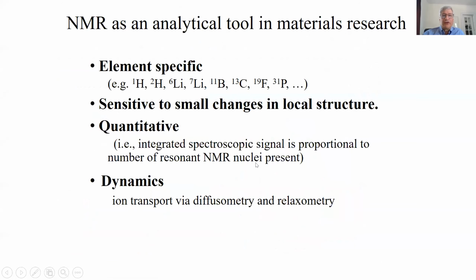So our laboratory uses nuclear magnetic resonance as a primary analytical tool. It turns out that nuclei that you can look at are very common in battery materials. So this is kind of a happy coincidence. The NMR technique is very sensitive to small changes in local structure. It's quantitative. We can look at various peaks of the NMR spectrum and get an idea of the so-called phase diagram, the different phases that make up the material that we're looking at. It's also very good for looking at dynamics. If you're looking at new electrolytes, you want to understand how the ions move and how well they move. So NMR turns out to be a very useful technique to characterize that.